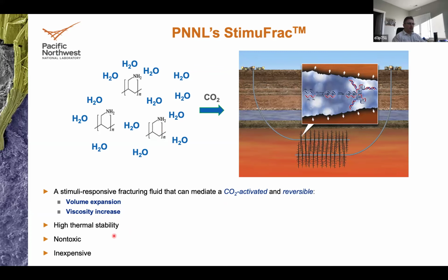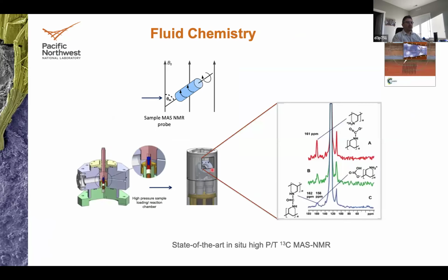The polymer is highly thermally stable. We have been able to get it up to 400 Celsius, limited by the operations of the vessels. But at 400 Celsius, we have the chemistry going and reversibility of the reaction between CO2 and the polymer. It's a non-toxic polymer. That's why we call it green. And also it's about 80 cents a kilogram. So it's fairly cheap. We use 1% of this polymer in water. That's everything about the solution. It's a very simple fracturing fluid.